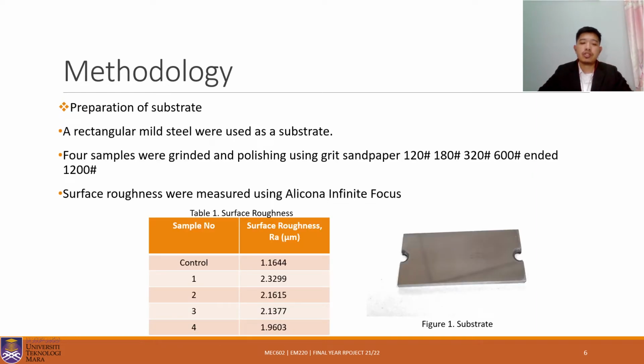The methodology for this study is: number 1, preparation of substrate. A rectangular mild steel was used as a substrate as shown in figure number 1. 4 samples were ground and polished using grit sandpaper 120, then 180, then 320, 600 and ended with 1200. The surface roughness was measured using Alicona infinite focus and tabulated in table number 1. As you can see here, sample number 4 had the lowest surface roughness among the other samples.